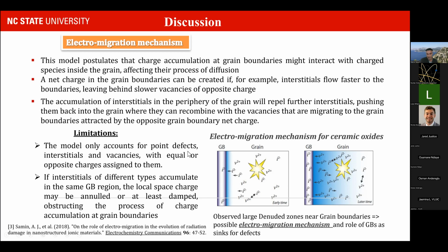It only accounts for point defects, interstitials and vacancies, with equal and opposite charges assigned to them. And that's not the case for magnetite, for instance, or these oxides where you have anion interstitials and cation interstitials that can be very fast also, and that can also go to the grain boundary. If that happens, this space charge will be damped, if not annulled. So in the end, we don't have a clear answer of why or how the defects are extremely mobile in the oxide, much more than in the metal. There are more experiments to be done and more simulations to be done, but magnetite is causing a lot of problems to modelers.